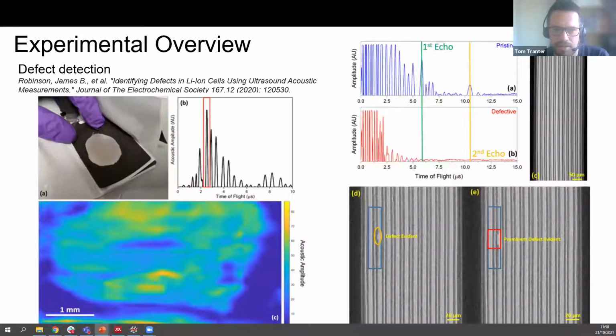We can also do defect detection. Here we actually got a cell and made a hole in the electrode, and we can clearly see that the acoustic response is different there. So this could be a technique that's used for quality control as batteries are being made. And then here's one that we didn't purposefully insert a defect, but we found one anyway. So just proving the technique.